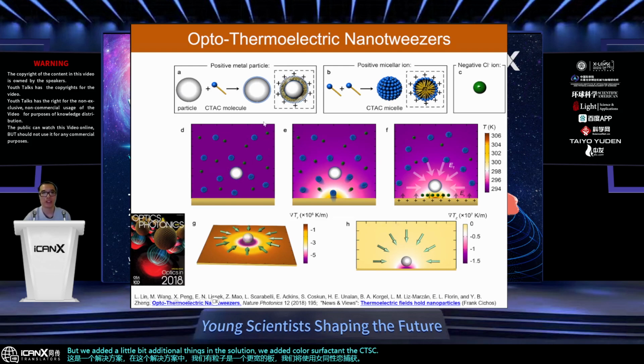One role is that they coat the particle, so the particle becomes charged, positive charge in this case. Another role is that they form micelles, the small particles made of this molecule only, so they also have positive charge. And in this solution, we also have negative chloride ions, which have negative charge. So we have three types of particles with different charge in the solution. When we hit the laser beam in figure E, we create a temperature gradient. At the center of this substrate, it's getting hot. When you move away from this center, it becomes colder. So you create this temperature gradient.